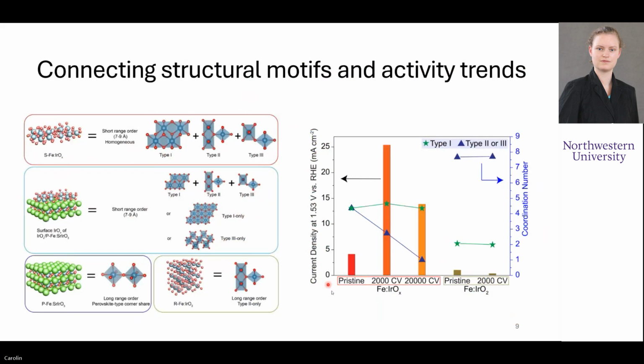For comparison, we also have the bulk strontium iridate perovskite, which has long-range order and shows these perovskite type corner sharing octahedra. And our bare iridium oxide, which is the rutile structure and shows the long-range order type 2 only. Now, on the plot on the right, you can see the current densities, i.e. activities of our different catalysts, pristine ones, and then after certain times of using them, compared to the pristine iridium